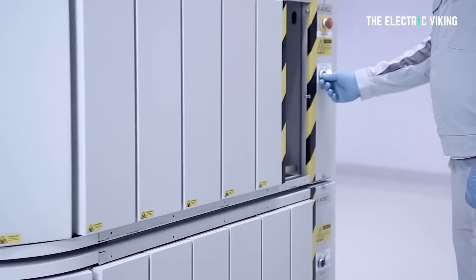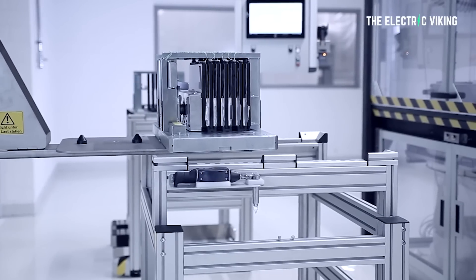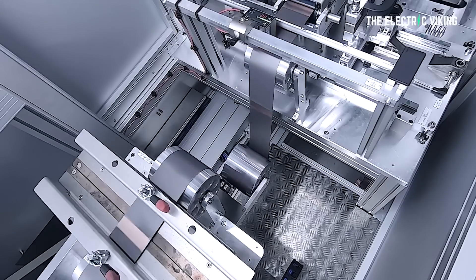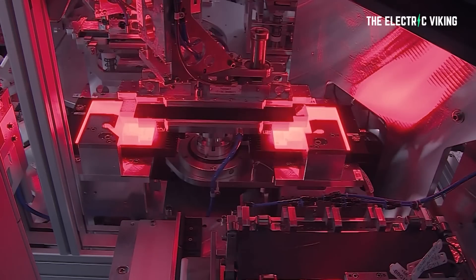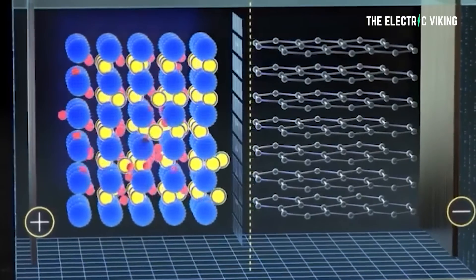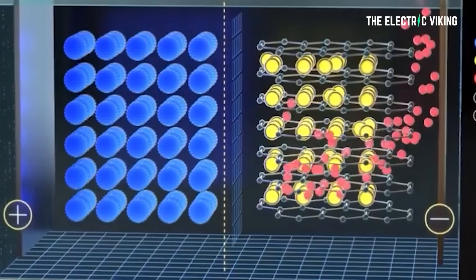So after each charge-discharge of the battery, tiny cracks eventually begin to form. They subjected those cathode materials to extensive analyses at the Advanced Photon Source, or APS, and Center for Nanoscale Materials, or CNM — Department of Energy Office of Science user facilities at Argonne. Different x-ray analyses were carried out at five APS beamlines, and it turned out that what scientists had believed were single crystals, as evidenced by electron and x-ray microscopy, actually had boundaries inside of them. Scanning and transmission electron microscopies at CNM verified these findings. When we look at the surface morphology of these particles, they look like single crystals, said physicist Wenjun Liu. But when we use a technique called synchrotron x-ray diffraction microscopy and other techniques at the APS, we find boundaries hiding inside of them that they previously didn't know were there.